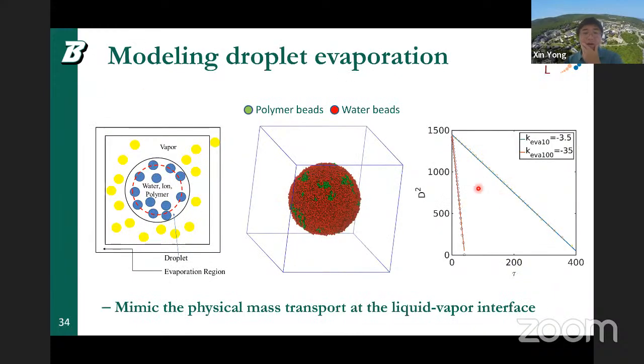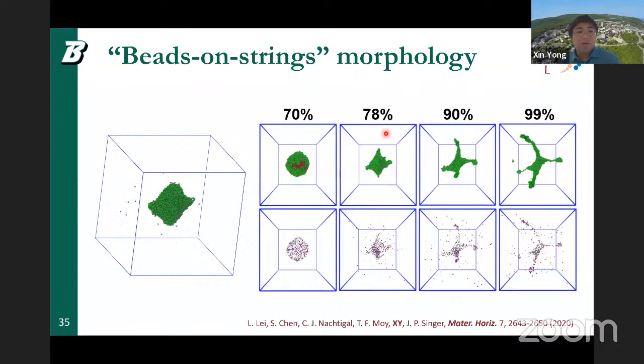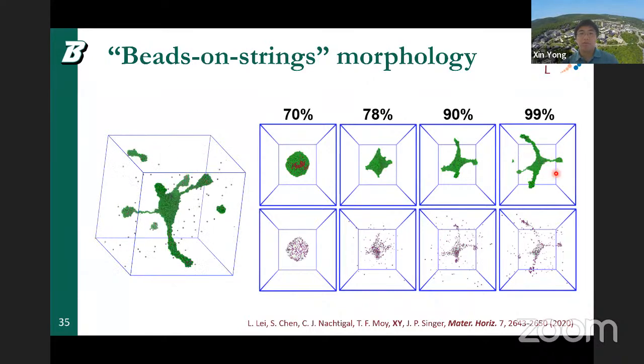So as we can see here, when we apply this, as the droplet shrinks, the charge gets concentrated, and then they will start to deform the particle and the polymer. And so we see that when we carry out the physical evaporation, we observe a very typical bead-on-string structure with a central mass and then a filament attached to it.